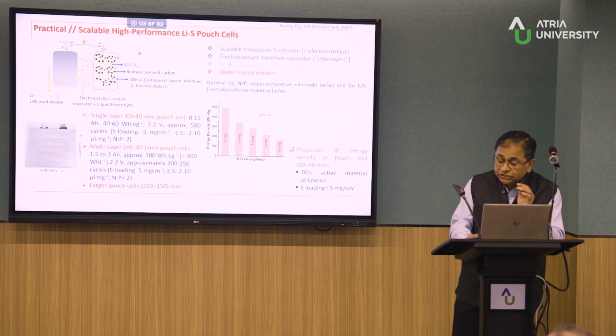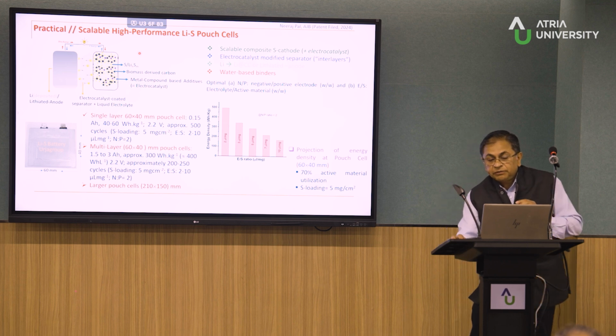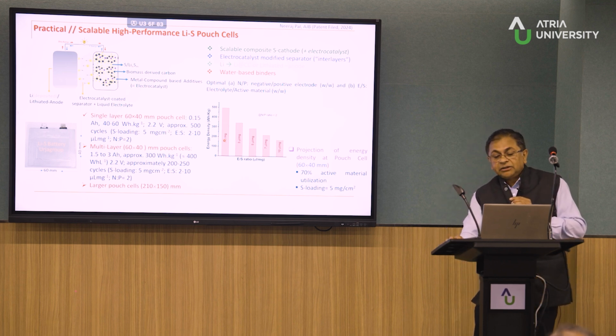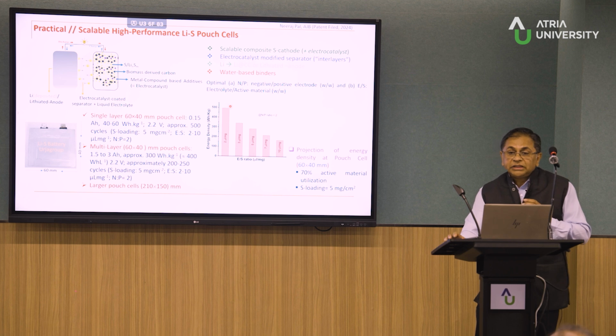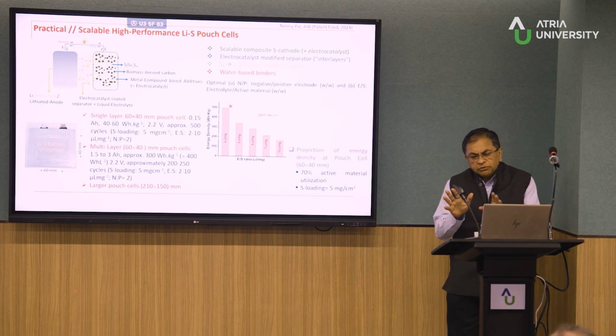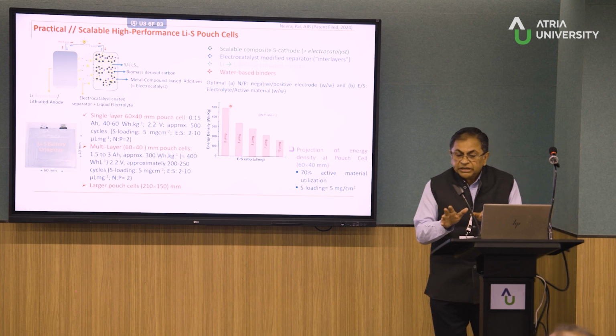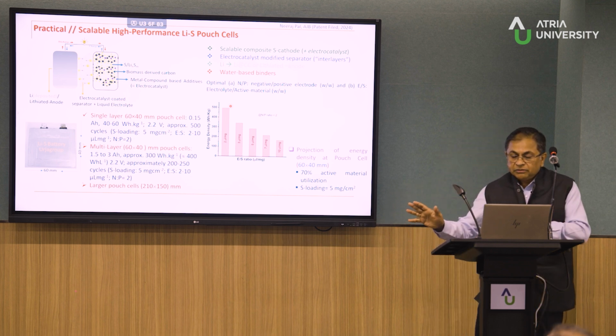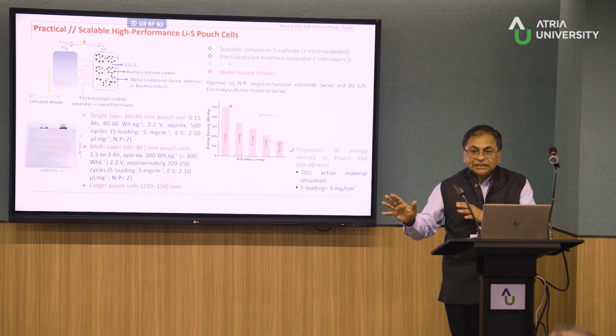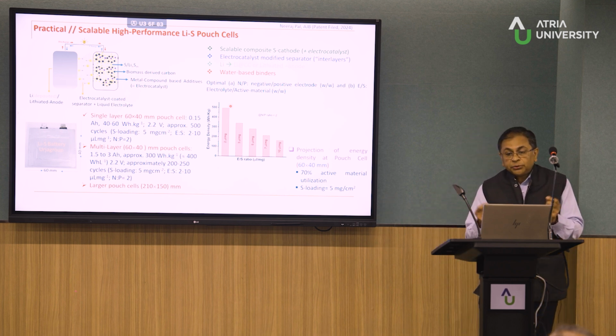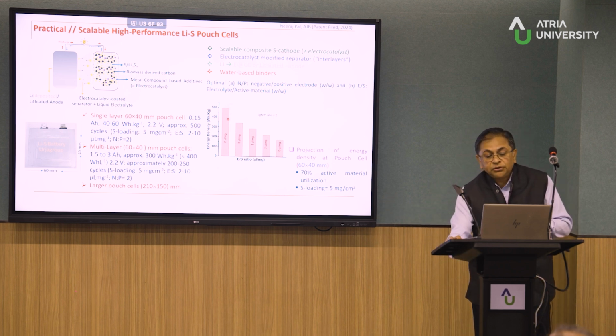Actually, we made some projection studies, right? If you load less electrolyte, your capacities may be very high. But then these are projections at roughly 3 to 5 milligram per square centimeter. But the industry, I think, wants more than this, close to about 10. Now, 10 means a thicker electrode. I don't think your batteries are going to work at such high loadings. Capacities may be high. This is all good for small cells.